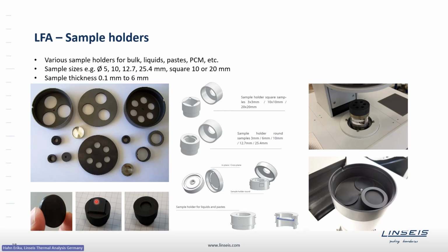For the sample preparation, you need to coat the sample on both sides with some graphite spray to maximize the absorption of the thermal energy shot out by the laser or the xenon lamp. Then we have here the specially designed sample holders, where you just place the sample on top, and we make sure that the sample is in as little contact as possible with the sample holder. We have here a lid closing just the side so that no excess light hits the infrared detector.